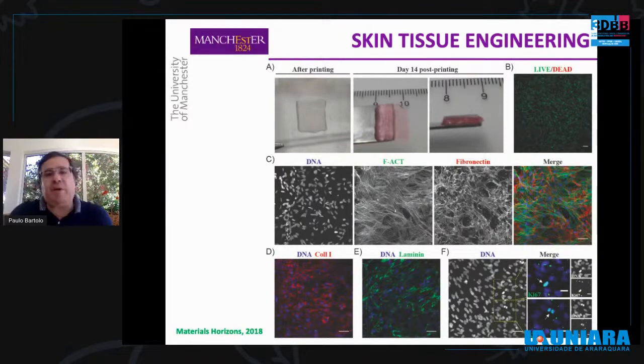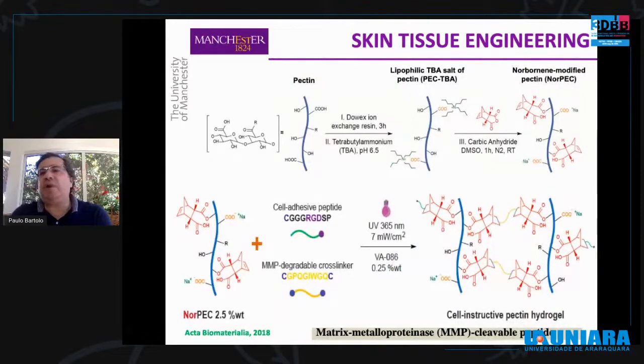But we were not totally happy with the chemistry. So methacrylate polymerization is a chain-growth polymerization process, inhibited by oxygen, creating non-homogeneous networks, characterized also by relatively slow reaction rates. So we decided to investigate a different chemistry. We focus on thiol-ene polymerization, which is a step-growth polymerization process, more efficient, faster, and also not inhibited by oxygen.